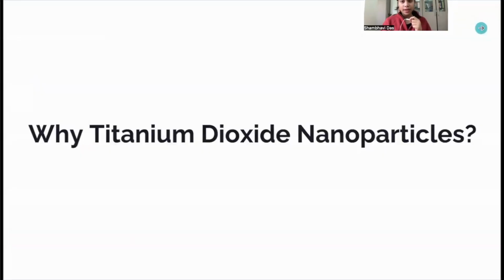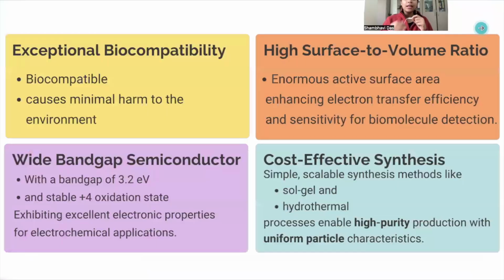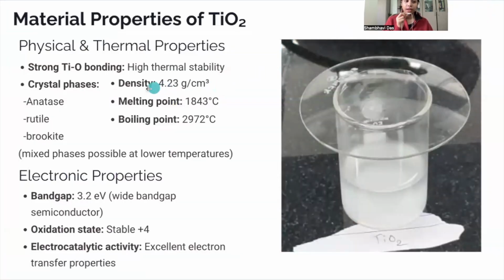Why titanium dioxide nanoparticles? Well, there are some properties of titanium dioxide nanoparticles that are ideal for sensing, such as its biocompatibility and how it causes minimal harm to the environment, its large band gap and its plus 4 oxidation state, the high surface area it has, and also the cost effective synthesis. We can produce titanium dioxide using methods like sol gel and hydrothermal and still ensure high purity and uniform particle characteristics. Here are some of the material properties of TiO2.